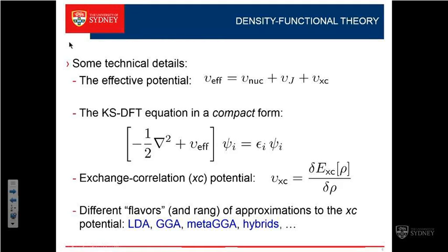Hybrid functionals are really very, very good, state of the art, various sorts again, but if you're doing a calculation, it may take you 100 times longer than the GGA. So a lot of people will calculate large systems using the GGA, and if you need accurate calculations, in particular for band gap values, like semiconductor band gaps and optical transition defect levels, then nowadays people expect you to use accurate hybrids.